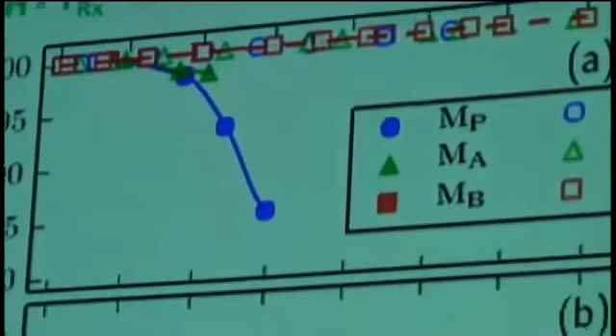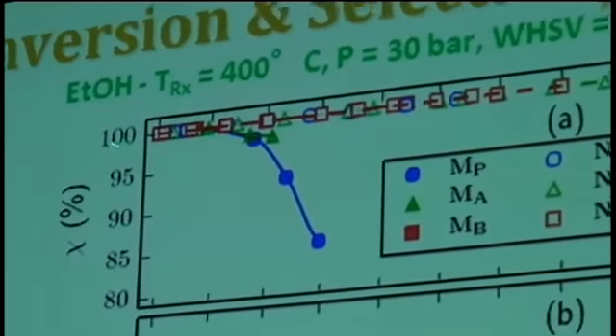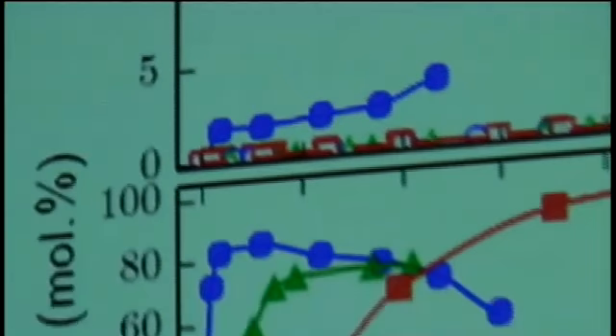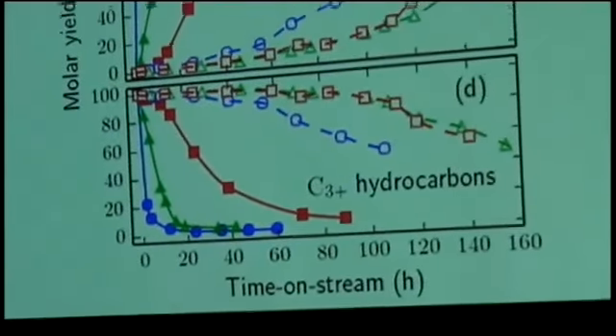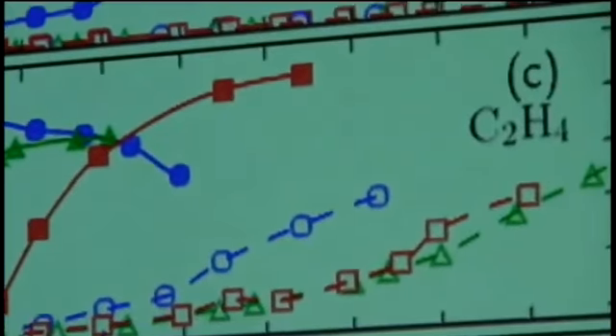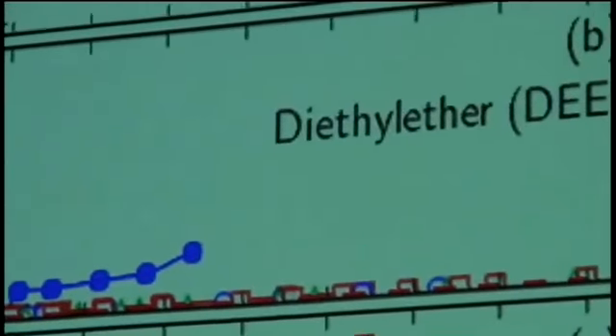Again, we don't want to do a kinetic study, we just want to push the catalyst as fast as possible to coking and analyze what is coming out. So the first thing here, you see that this is the conversion as a function of time on stream. So all the catalysts under these conditions are relatively stable for a decent period of time. The first to surrender is the catalyst, the micron-sized catalyst that doesn't contain any mesopores. The activity just falls down.